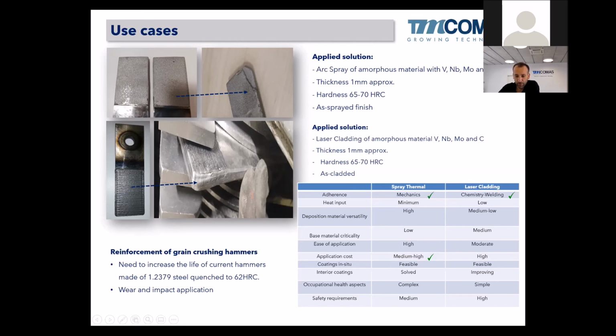the laser hammer has the same amorphous material with vanadium, niobium, and molybdenum carbides, about 1 millimeter in thickness, the same hardness, and obviously as clad. The same material applied by laser, it's still running. So in theory, we have improved a lot. I'm telling you in theory because the hammer is still running, so we still don't have feedback from the customer.